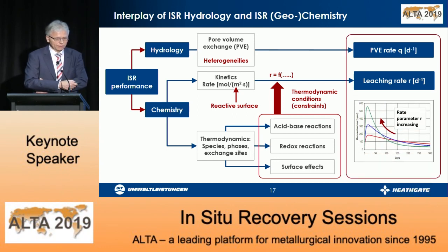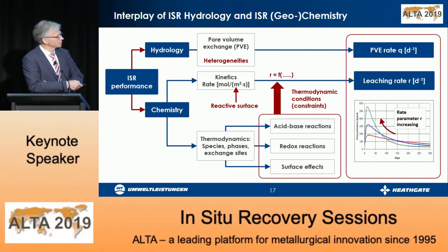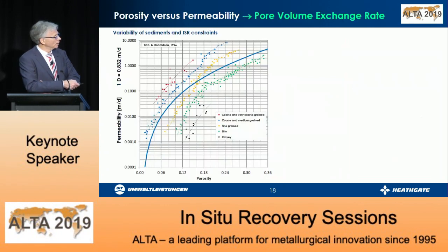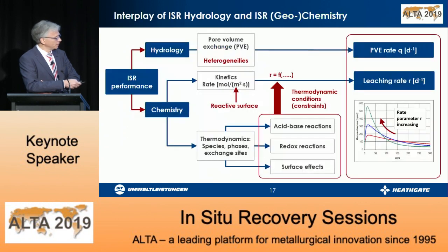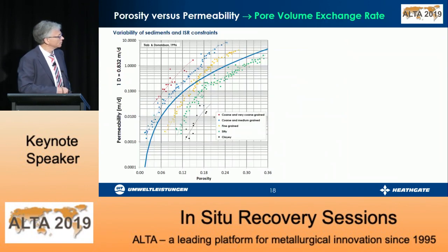In general, an increasing leaching parameter leads to a much faster recovery of your metal. And what we are doing is to increase the leach parameter as much as possible to minimize the lifetime of a well field and to make the in situ recovery most economic.